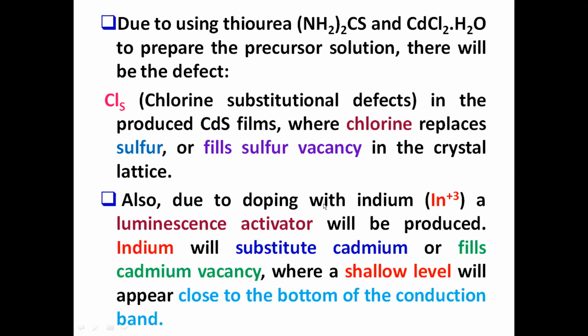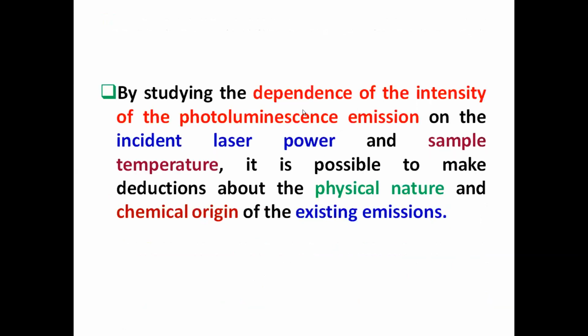Also, due to using indium as a dopant, there will be a shallow donor near the bottom of the conduction band, and this is good because it is used to increase the conductivity of this material. By studying the dependence of the intensity of the photoluminescence on incident laser power and sample temperature, it is possible to make deductions about the physical nature and chemical origin of these emissions.